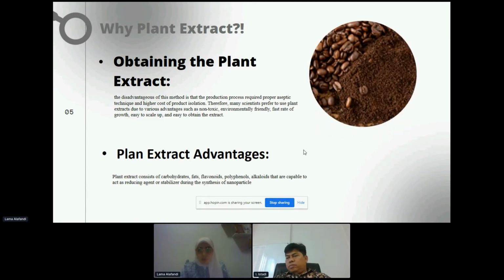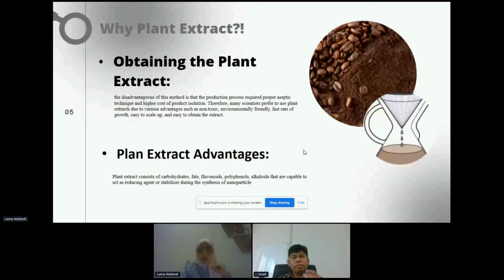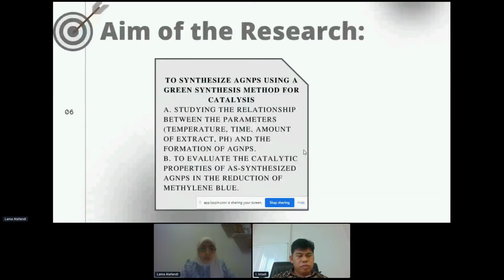For example, using coffee extract, we only needed to get the brewed coffee from the market. We need to filter it, and dilute it first with ultra pure water. Then we precipitate it for a few hours and then filter it, and it will be ready to use as a reducing agent. Some other advantages of plant extract: it consists of carbohydrates, flavonoids, and some alkaloids, such as caffeine in coffee extract, and they are capable of acting as reducing agents or stabilizers during the synthesis of nanoparticles.